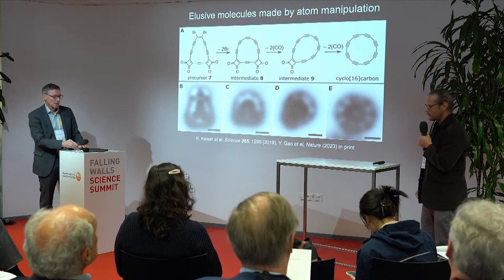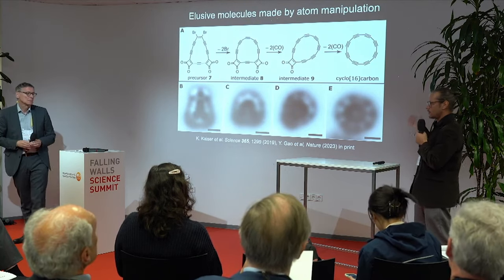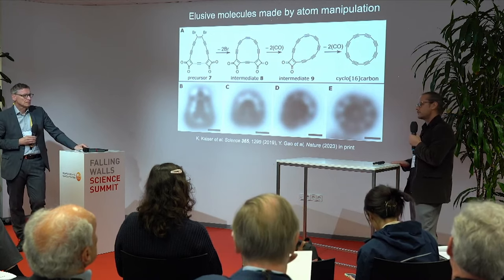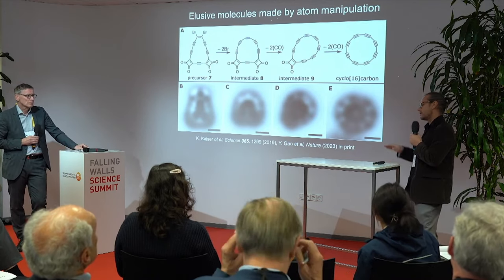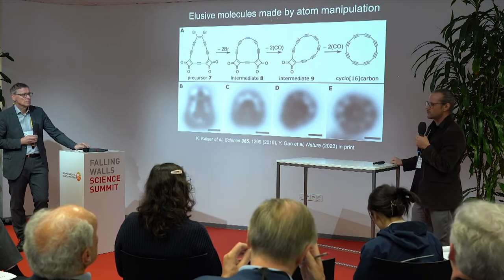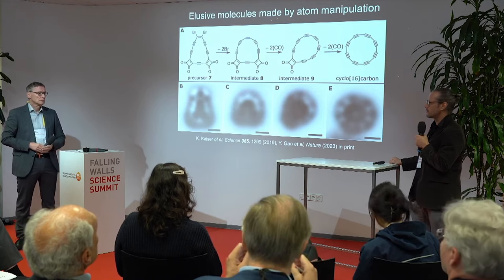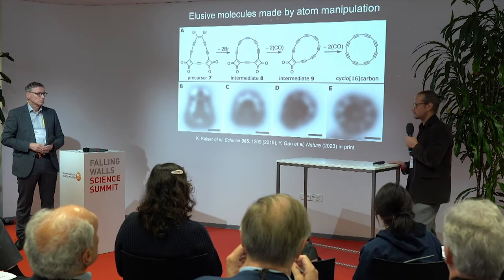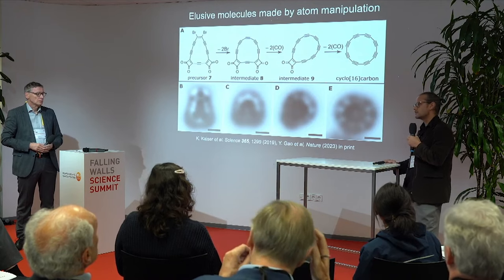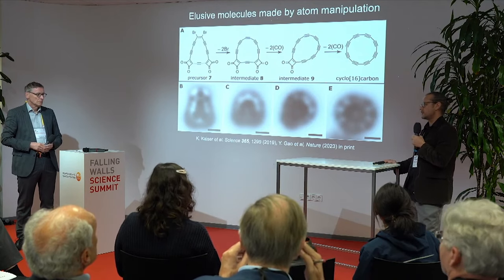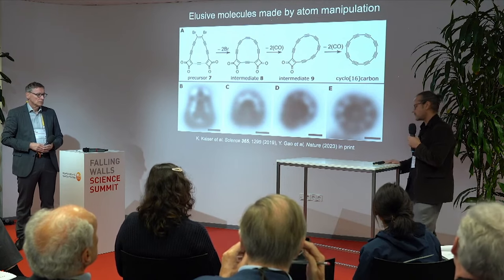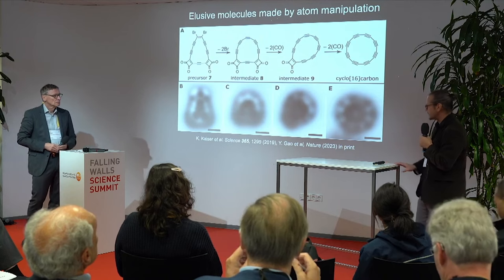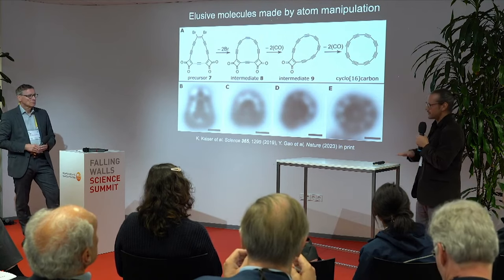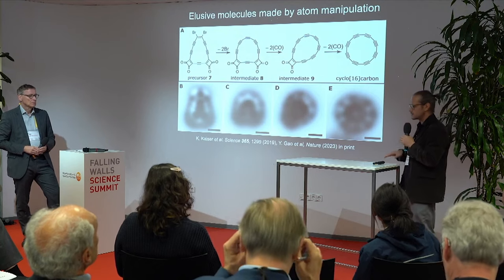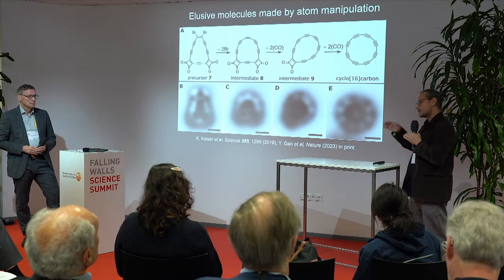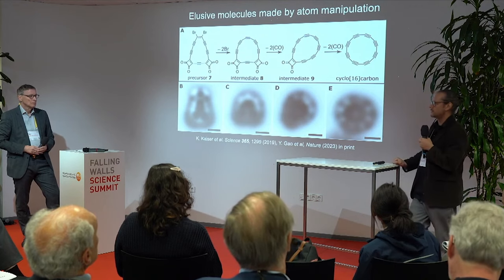Thanks for the question. So if we study these very reactive molecules that you cannot make otherwise because they're so reactive, we have to use very chemically inert surfaces so that they don't form bonds to the surface. And here we use often sodium chloride, so just table salt that we grow as a thin layer on our single metal single crystals. Or sometimes we use even a monolayer of xenon that's even less reactive if we want to study these molecules on the surface. And one main limitation, since you ask about it, so this technique is really good to study planar molecules. That's more from their imaging mechanism. If the molecules get into 3D, we can basically only look at the surface. It's a very surface-sensitive technique.